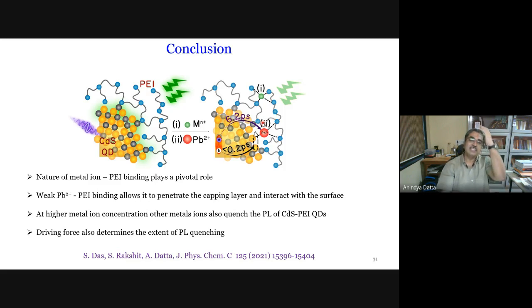And the reason why there is selectivity for lead at such low concentrations is that the PEI is a strange customer. It does not like to interact with lead. So lead is able to get through this capping agent and reach the surface. While the other metal ions that we studied, they love PEI. So they get trapped and they are not allowed to approach the surface at all. That is why they cannot work. If they reach the surface, they would have quenched the PL as well.